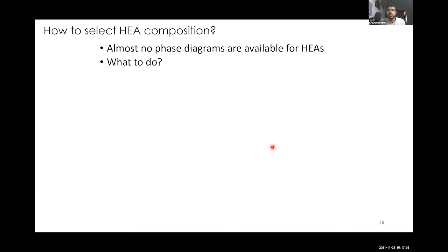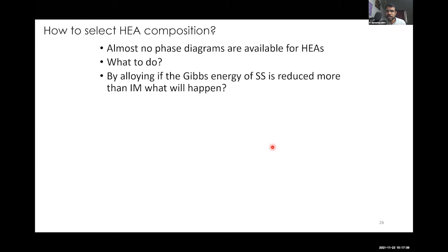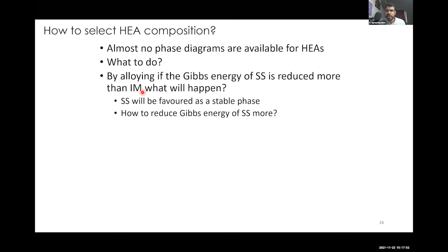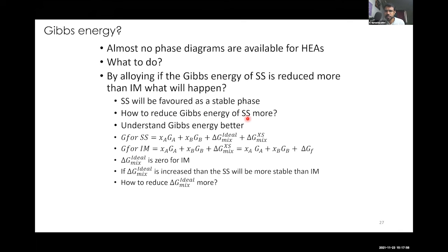So now we have understood that there are almost no phase diagrams available for these alloys. So we can look at the Gibbs energy of the solid solution and try to minimize it. Therefore, intermetallic phases will not be stable. How to minimize the Gibbs energy of the solid solution is what we are going to see. How to reduce the Gibbs energy of the solid solution more? For that, we have to understand Gibbs energy better. So Gibbs energy for a solid solution has this kind of expression.